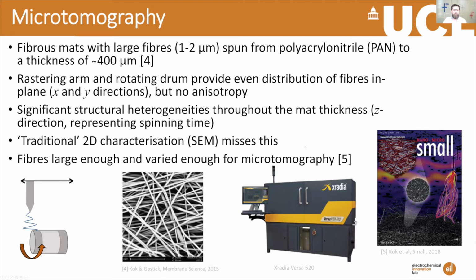So first of all, Matt made these electrospun materials. There's actually quite large fibers for electrospinning. I should say electrospinning normally produces fibers just less than a micron, which of course increases the surface area for these electrodes, which is great, but it can have consequences on the permeability of the mats as well. Anyway, these included quite a lot of large fibers above 1 micron, and this is spun from polyacrylonitrile, which is quite a typical polymer for these carbon felts.